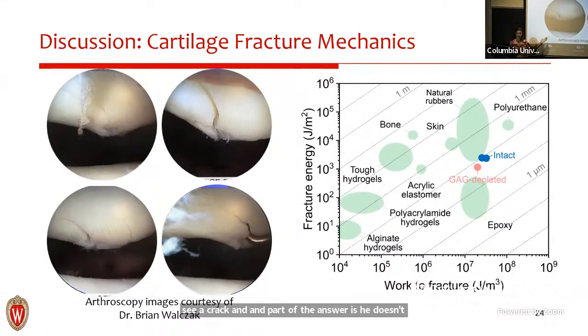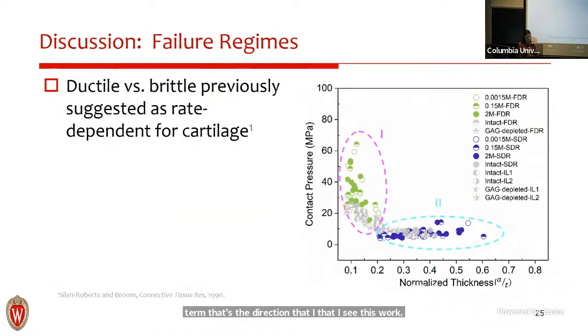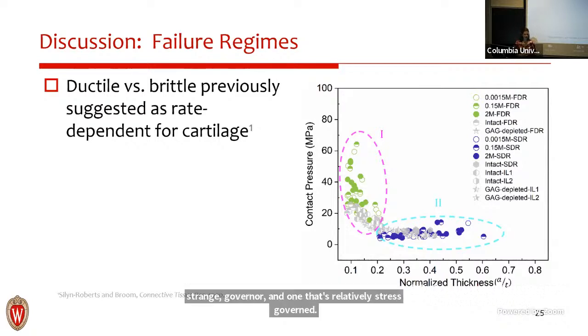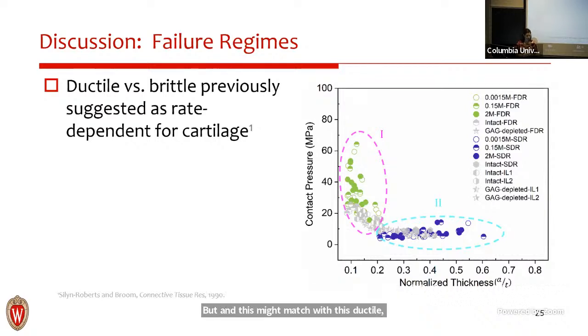So one of the things he does is takes pretty images, but the direction that I definitely see this work going is coming back to this idea of when should we be concerned about a crack in cartilage? And what might we do? Is there some way to arrest a crack or provide some other intervention, especially if the surgeon is in there anyway? So longer term, that's the direction that I see this work going. Shorter term, we've got some other work to do. For the failure regimes, I propose these two failure regimes, one that's relatively strain governed, one that's relatively stress governed. And this might match with this ductile versus brittle. This idea has been suggested before, actually quite a while ago, so early 90s, where depending on the loading rate, you could consider cartilage failure as ductile versus brittle.